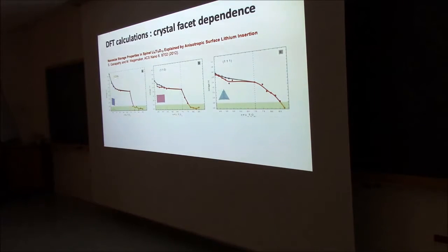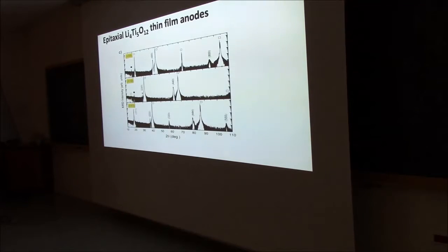Here they say in the 100 and the 101, at the surface it's lithium 7, and this is not possible. But if you do 111 facet, then you would be able to attach much more lithium there because of the arrangements of atoms there. So this was only prediction. So we said, okay, let's see if we can study that.